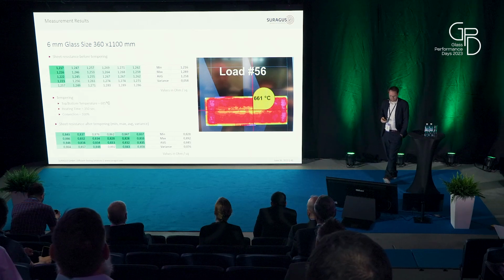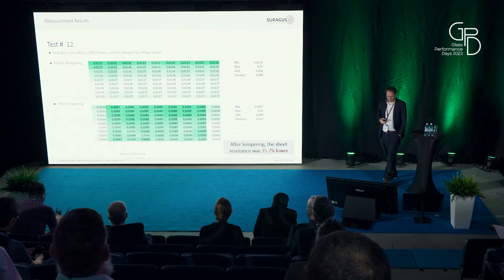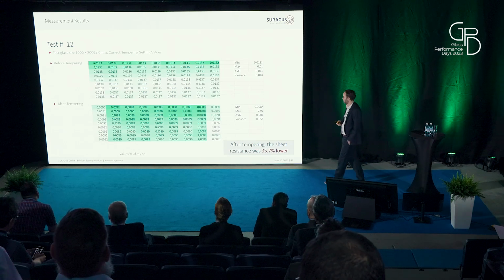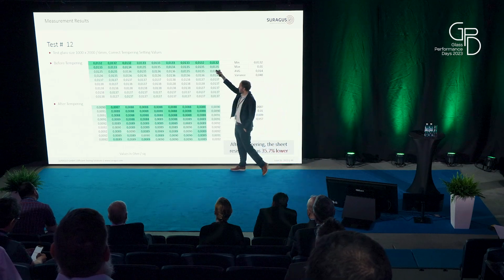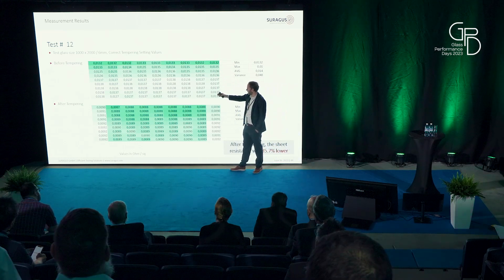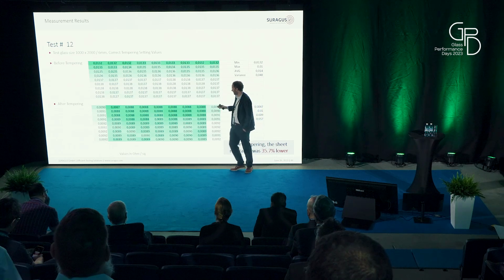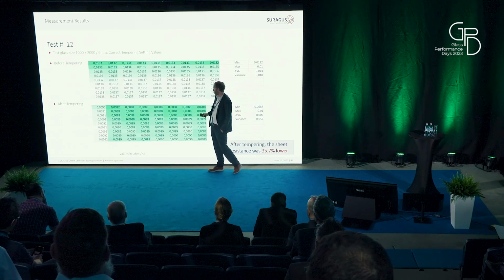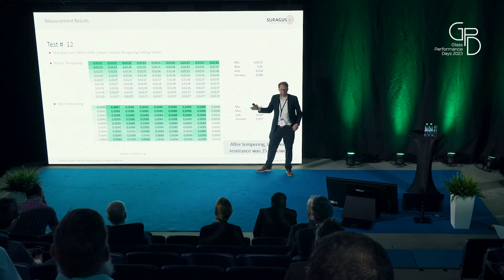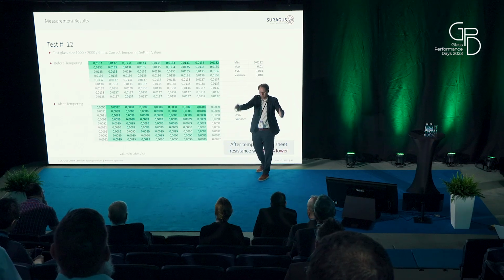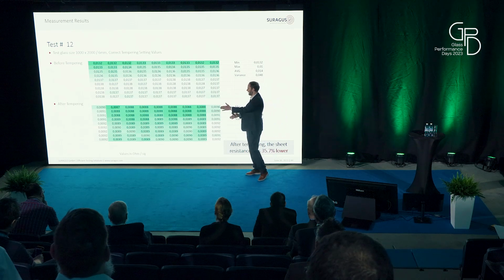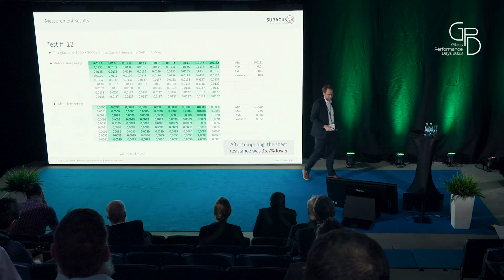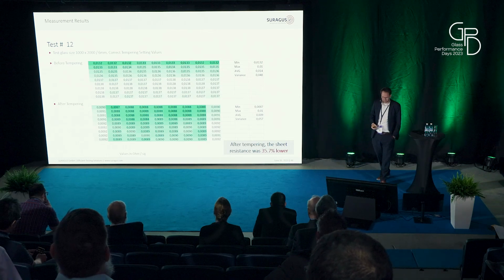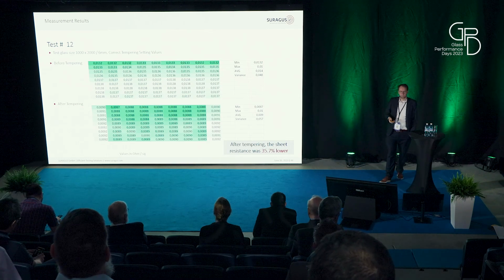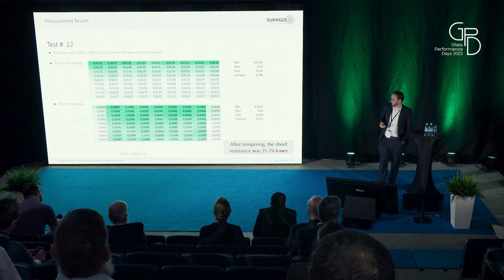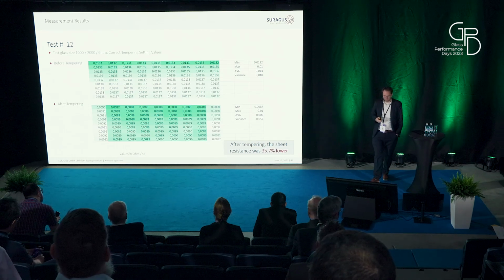Here's a 6 millimeter glass, and here is also another 6 millimeter glass where we took more data points. We see some slight variation in the silver coating before the tempering, and after the tempering it's more like another profile, where the outside is a little bit different. We see different processes here, and the sputtering also depends on how the glass was manufactured and how it ends up on the tempering table. There are a lot of differences. This is just the status which I present here. It was a lot of work to get this data, a lot of driving around, a lot of measurements with this portable device.